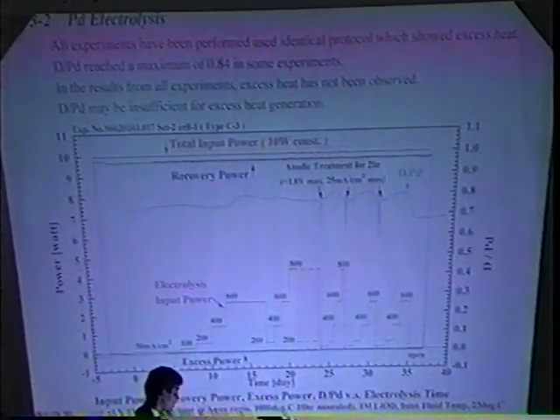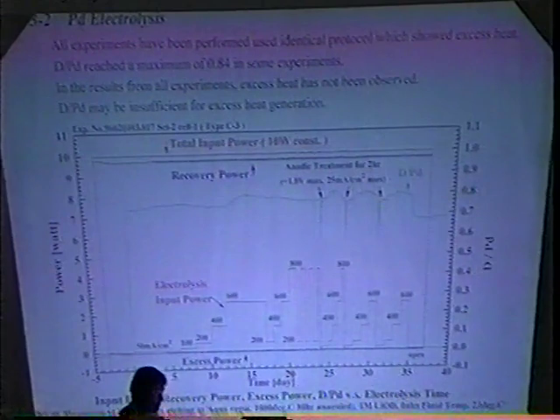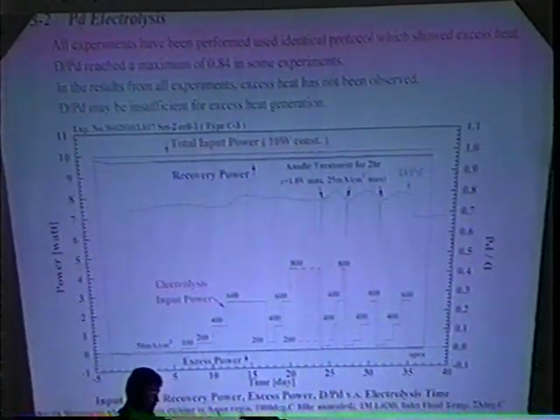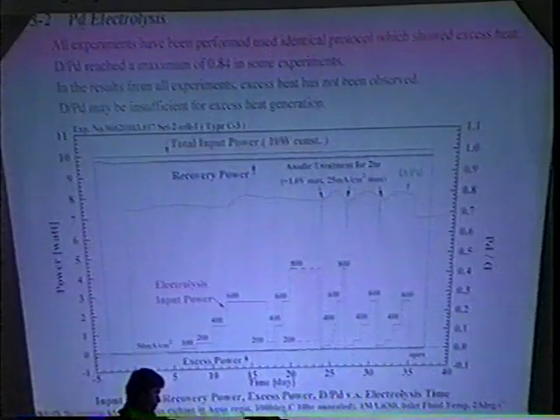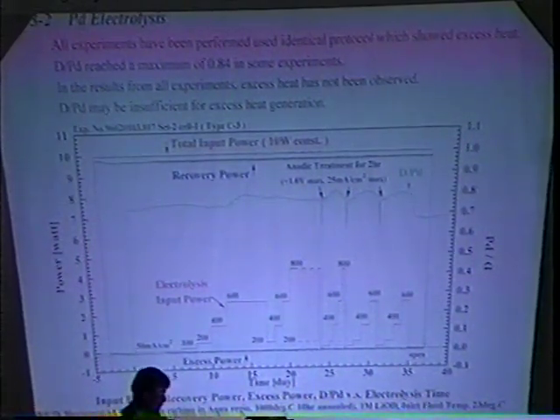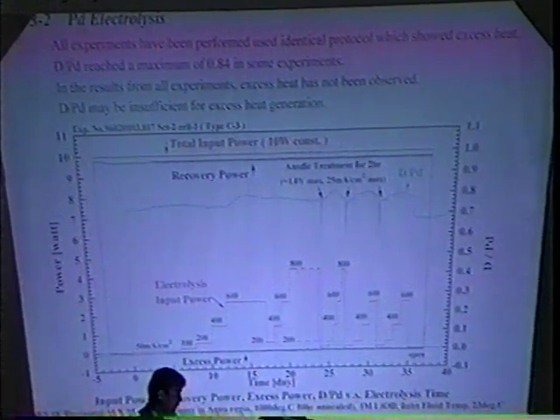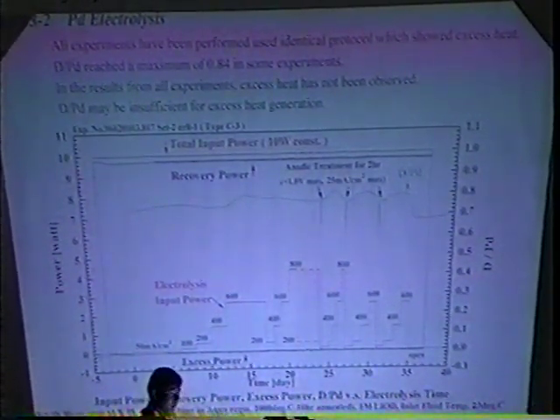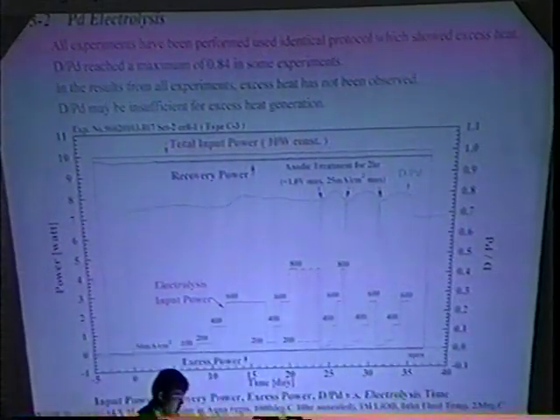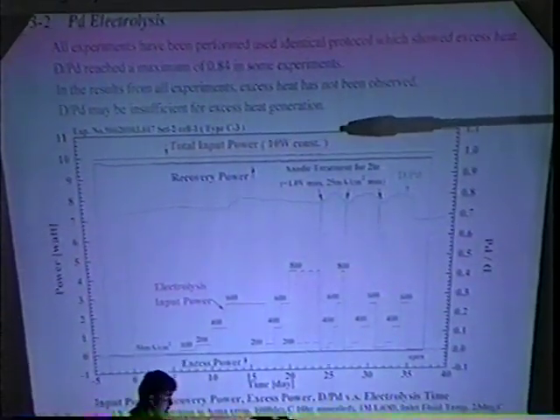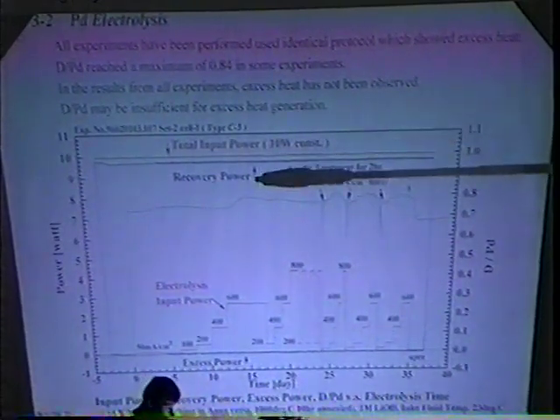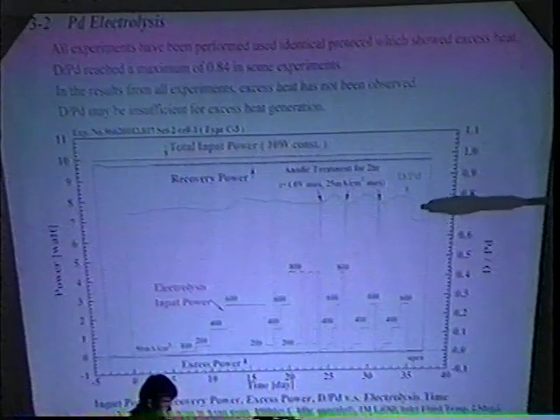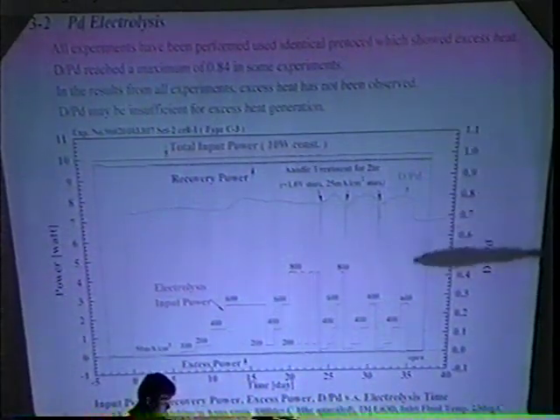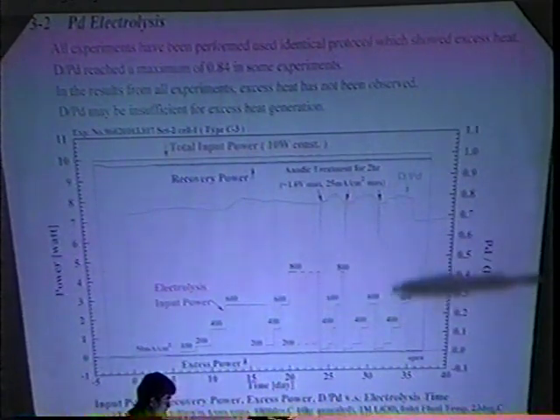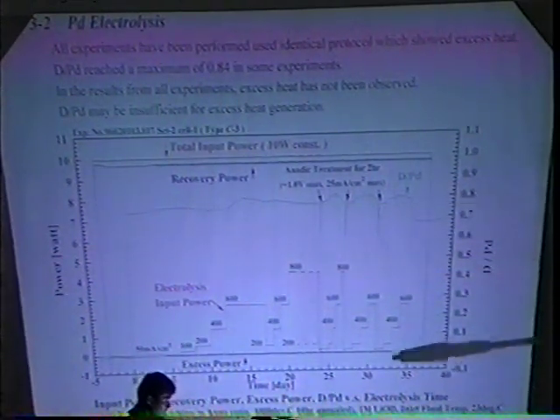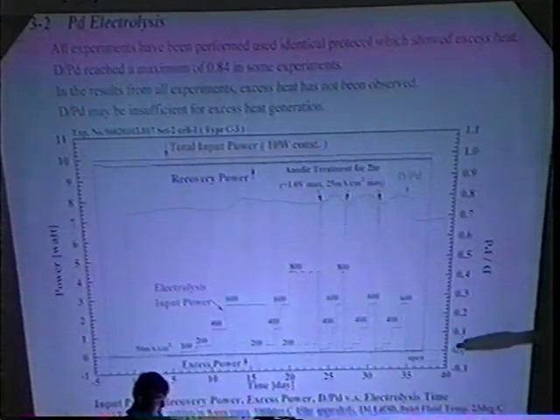Using palladium cathode electrolysis, all experiments have been performed using an identical protocol, which showed excess heat in prior fuel cell type electrolysis system experiments. This figure shows the typical result of palladium electrolysis using NHFCS. The red line is the total input power, blue is recovery power, green is D by PD, pink is electrolysis input power, and black is the calculated result of excess heat.